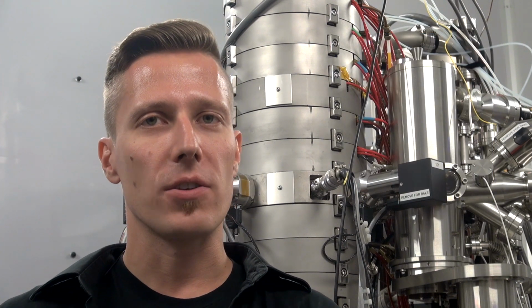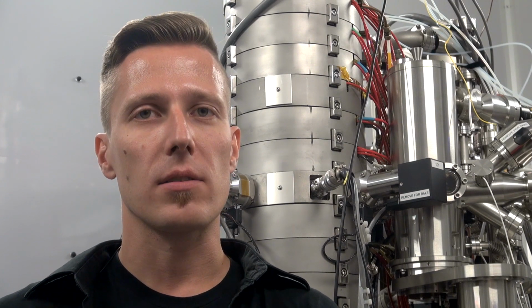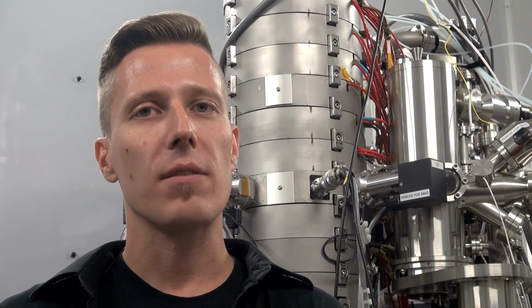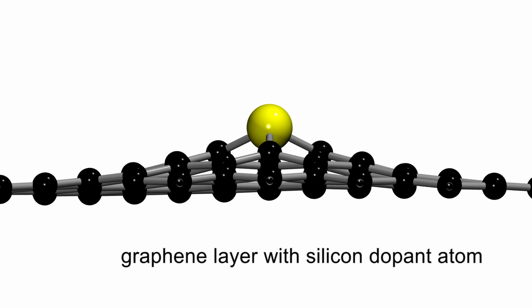The present work got started when Jani Kotakoski and I were looking at the stability of a related system under an electron beam. Our density functional theory simulations surprised us by predicting that a relatively low energy electron beam would be able to cause non-destructive changes near heavier dopant atoms, atoms of other elements that replace part of the carbon atoms in graphene and stick out of the structure.